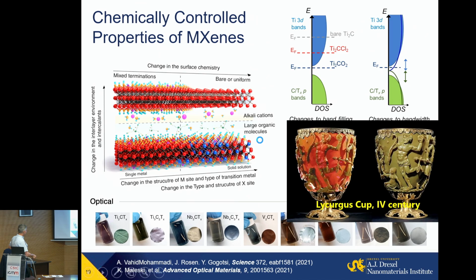And of course, they come in a variety of colors, complementing plasmonics. You see, titanium 2 carbon is red in solution, basically in transmission, and green in reflection. You add one layer of transition metal, titanium 3 carbon 2 now, and it becomes green in solution because its absorption band shifts from 550 to 780 nanometers. And you might be familiar with this, people claim the first example of human-made nanotechnology, where plasmonic gold and some silver nanoparticles in glass make this 4th century Roman cup, which is in the British Museum, red in transmission, green in reflection. Last year, the Nobel Prize in Chemistry went to inventors of quantum dots, and one of the 3 guys, a Russian, received it for metal nanoparticles, plasmonic in glass. Exactly what the Romans did quite a few centuries before him.